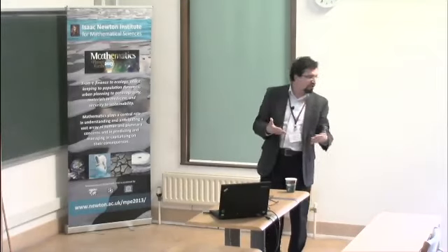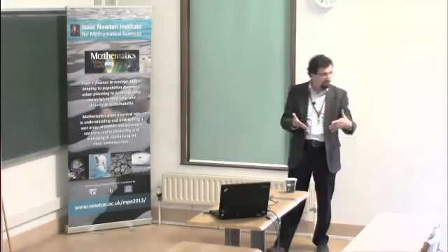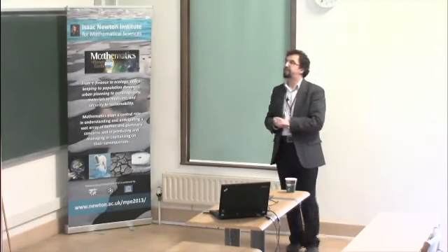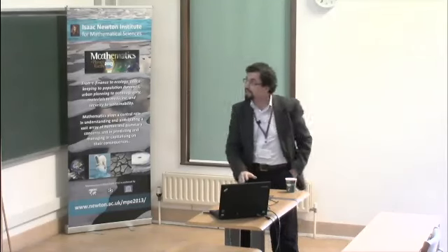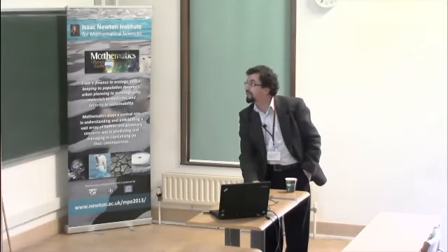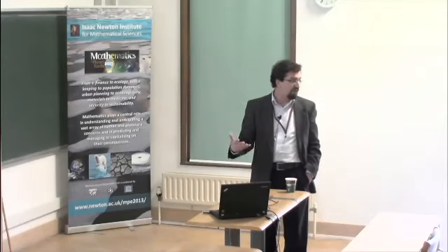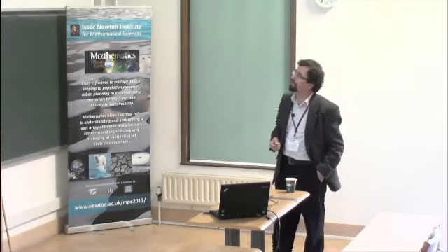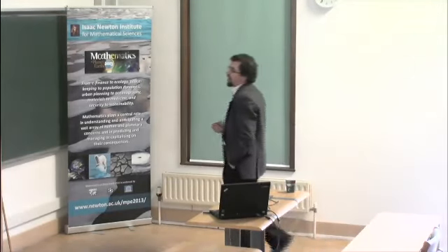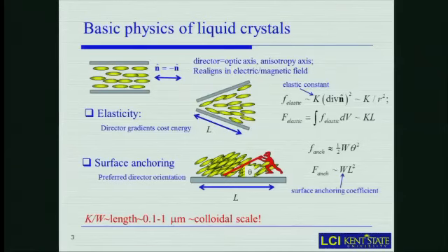So whenever you would like to change this orientation at the surface, you again need to perform some work. And from dimensional analysis, you would realize that this energy should be proportional to some coefficient, W, which is called the surface anchoring coefficient and is a function of the properties of the substrate and the liquid crystal, and the area of the interface over which you would like to realign the director.